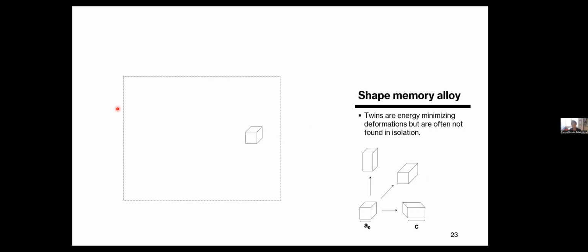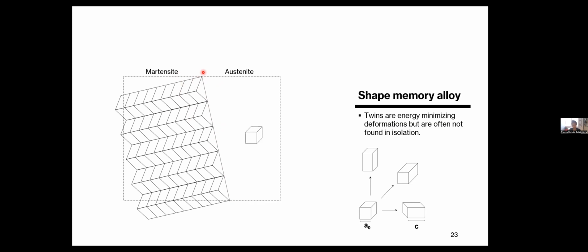Now if you cool the material, these lattices transform to a tetragonal variant, for example, and each of them can transform independent of each other, so you can have different orientations of the lattice that nucleate. When they collectively form a microstructure, both phases coexist and meet along a specific interface. Because these have different lattice geometries, this interface is going to be elastically stressed. As a result, they orient their lattices to form what is called a finely twinned microstructure, minimizing the elastic stresses at this interface.